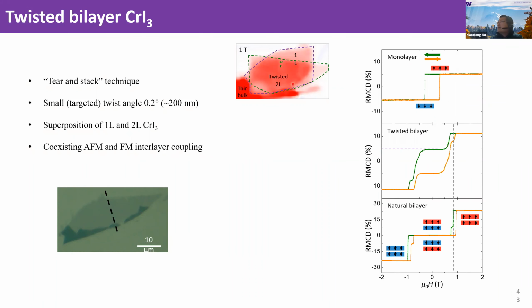I can perform measurements on the individual monolayers. This monolayer, for example, shows a very nice hysteresis curve, just like a monolayer. I can also measure a natural bilayer, shown at the bottom. But if we measure the magnetic circular dichroism signal, MCD, on this twisted bilayer, you will see a non-vanishing MCD signal at zero field.